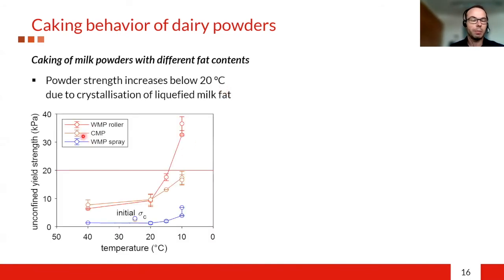Here I show you the unconfined yield strength as a function of the temperature for the 3 milk powders we tested. Here you can see the initial unconfined yield strength at the beginning of the tests. With heating, the roller dried whole milk powder and the cream powder increased a little bit in strength, and the whole milk powder did not do this. With decreasing temperature during cooling, below 20 degrees Celsius, the powder strength started to increase for the whole milk powder, the roller dried, and the cream powder also.